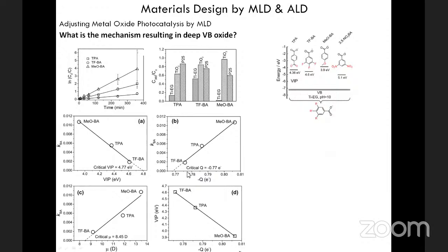What you see here is correlation of the rate constants and the ionization potentials. You see correlate very nicely. And the electron density at the anchoring group, the dipole, and the charge. And all correlates very nicely. So it was clear that the rate constants correlate with the electronic features of these molecules.